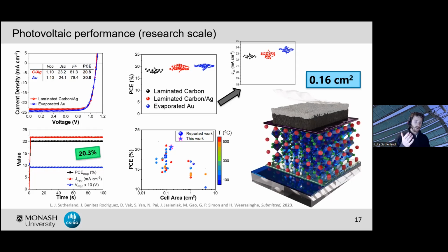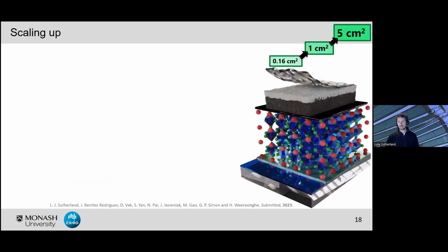However, the benefit of our bilayer electrode design is having the highly conductive silver film. And what's more, with the immense pressure that we are applying with the CIP, we then progressed to developing these larger area cells to see how they would fare against the literature. And so simply, devices fabricated exact same as before by simply cutting larger electrodes to fit the device size.